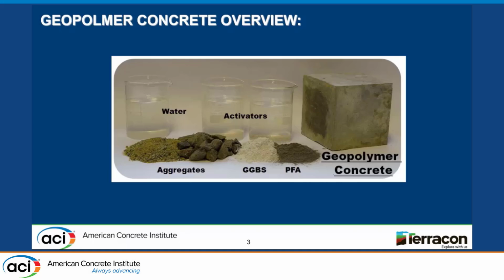and mixed with fine and coarse aggregate. We also have to have external heat, usually 70 Celsius, which is 158 Fahrenheit, to help develop and start the reaction. The external heat should be applied for 24 hours to 48 hours.